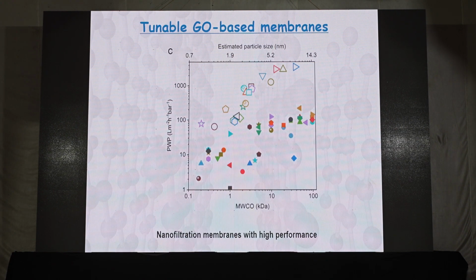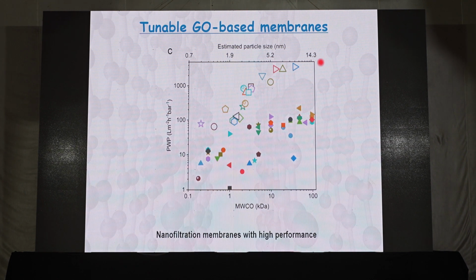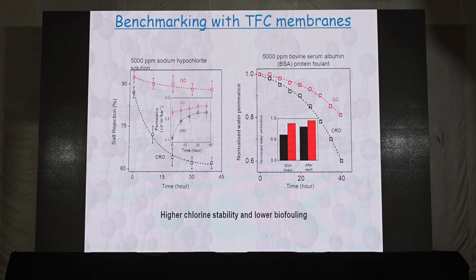Based on that, we found several methodologies. I will not go into detail how we do it, but essentially you create channels or membranes with different sizes, ranging from tens of nanometer to sub-nanometer, less than 1 nanometer. Then you saw that compared to the natural commercial or existing polymeric membrane, we have better performance in terms of flow and selectivity. Selectivity means basically the pore size.